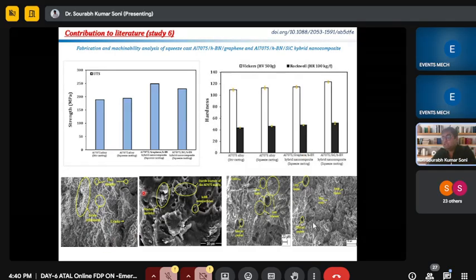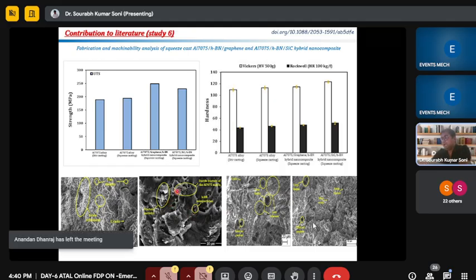So this is the fracture image of the specimen. Here we can see the HBN particles within some pores or some dimples. So we can say that these HBN particles are agglomerated or entrapped in the specimen. So that's why hardness is increasing, ductility is reducing, or UTS is increasing. We can interpret our data by highlighting this kind of fracture analysis.